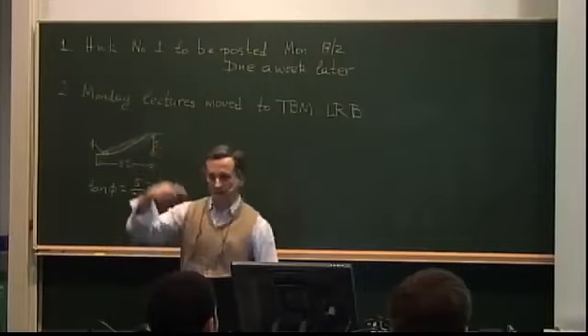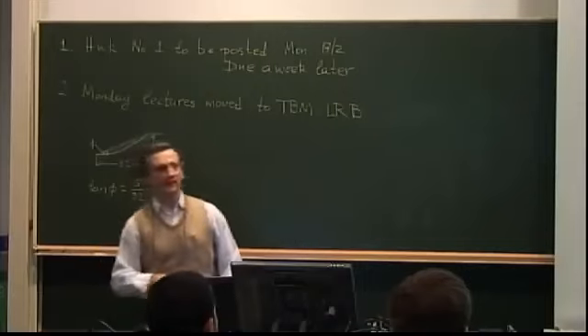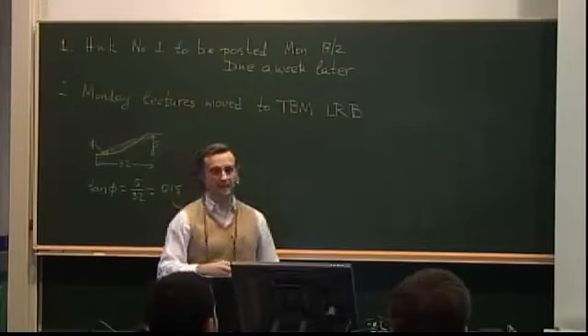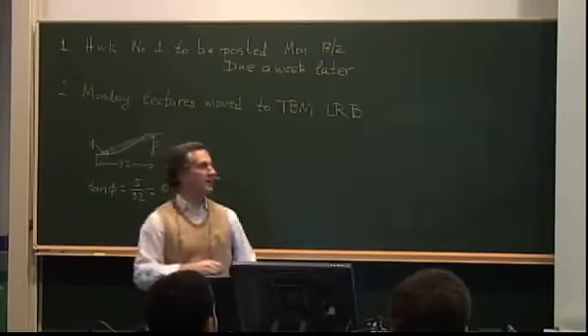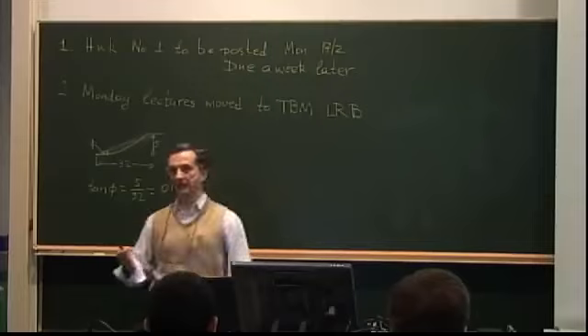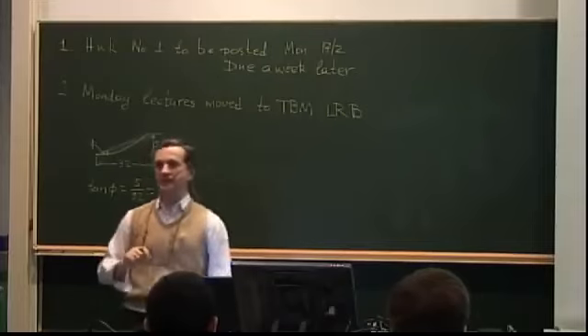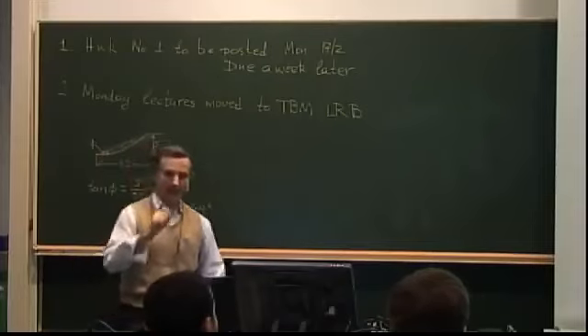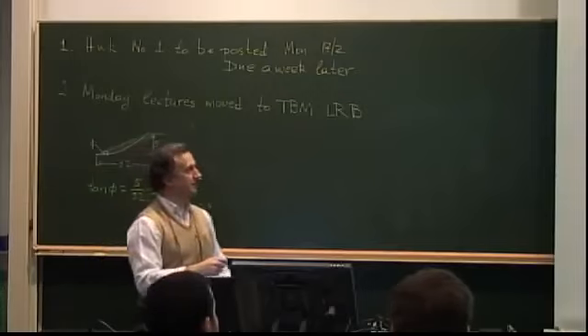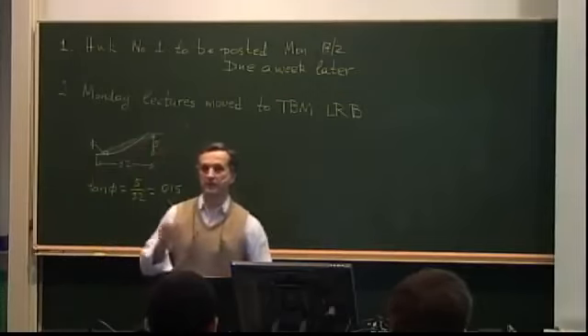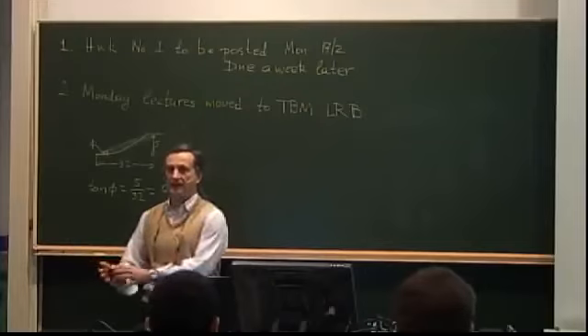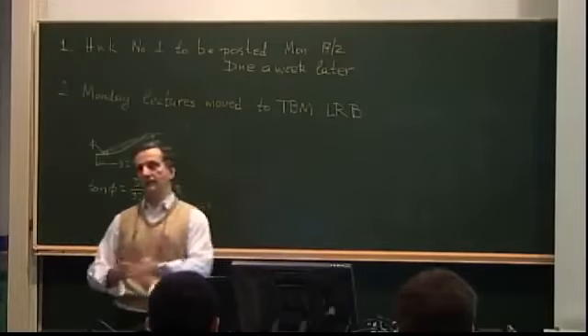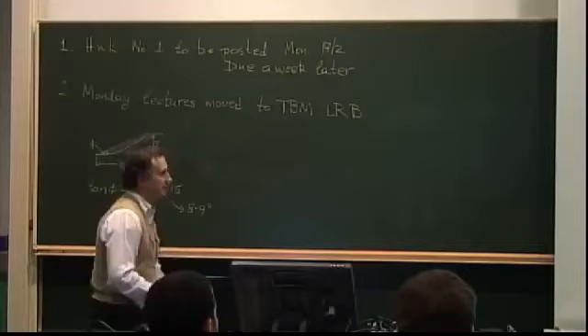In fact, there's a whole mathematical derivation that derives this and makes sure that this criterion, if you had an isotropic material, would give you the von Mises yield criterion. Again, it was arbitrarily chosen by these gentlemen, Steve Tsai and Ed Wu, so that there's a limiting case recovered by that criterion, and that was one of the main reasons there was a lot of criticism.